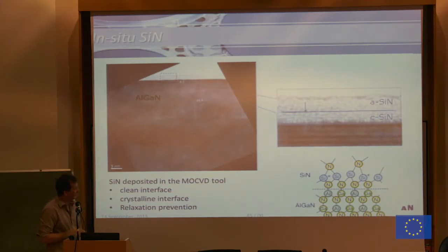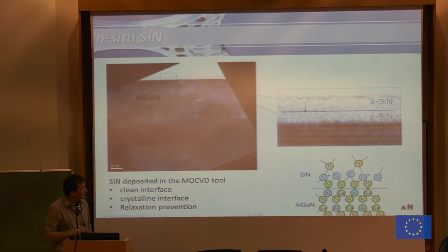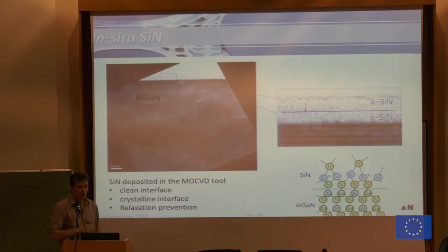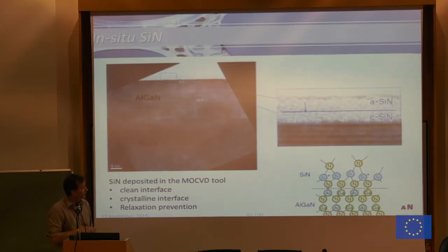And one of the nice effects of growing the silicon nitride in your MOCVD reactor is that the first few monolayers of the material are not amorphous, like what you obtain with PECVD silicon nitride and so on, but you can have some crystallinity. So if you remember the story I have told before on why a good passivation needs to have this specific atomic configuration, then of course having a crystalline starting layer there is beneficial.